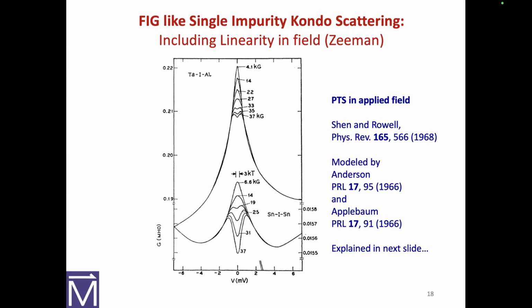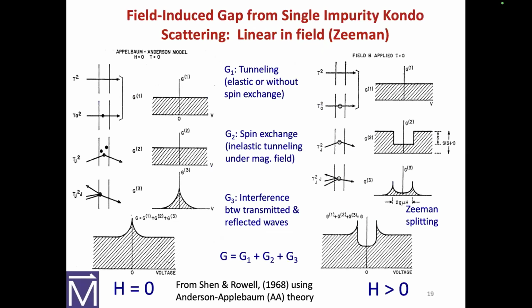What this is, is NIN tunneling with some magnetic impurities in the barrier. And just to remind you of what was shown, and it's been a popular area and it's been revisited again, is that you can certainly get a Kondo peak in the center, but what's important is this Kondo scattering does give you a linear splitting. It does split linearly with applied field because it is a Zeeman splitting. This is stuff, if you don't know it, it's really fun and worth reading when you can actually get through a paper and they explain things for you.